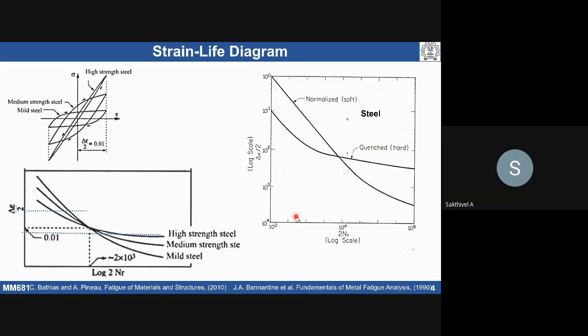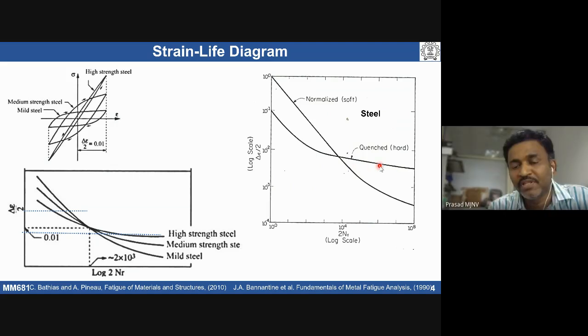Sir, can you please explain why martensite has less life in low cycle fatigue? See, if we talk about low cycle fatigue, cracks can easily be initiated. We are already subjecting this material to stress above yield stress, which means plastic deformation is going to take place. Because of plastic deformation, a crack has already been initiated. The crack propagation is very fast.